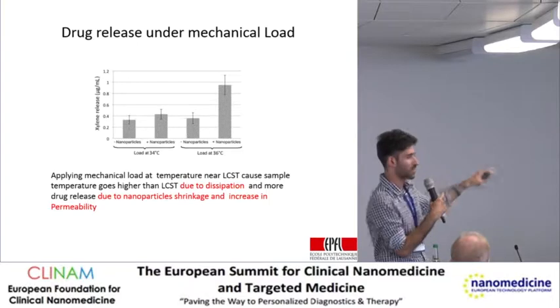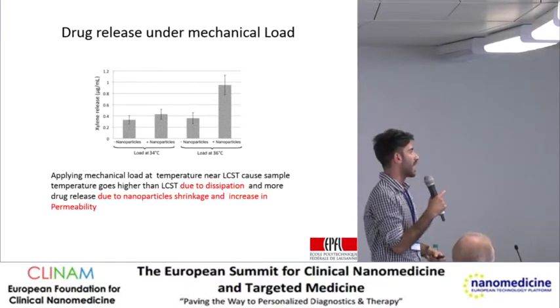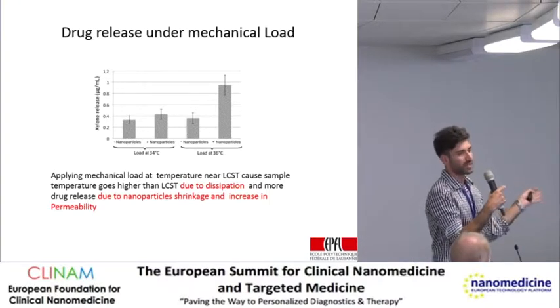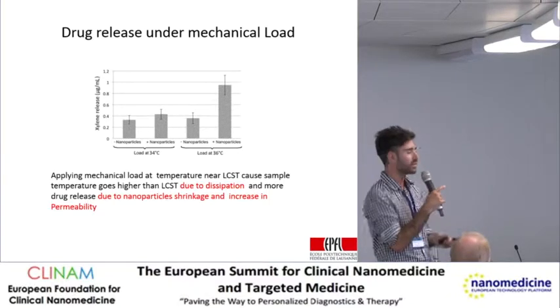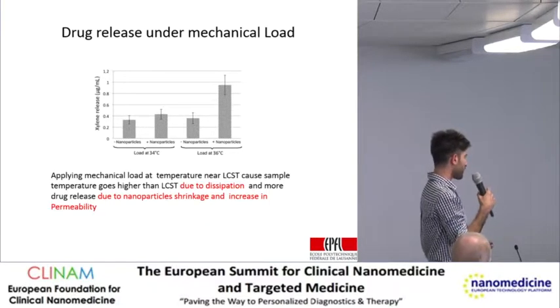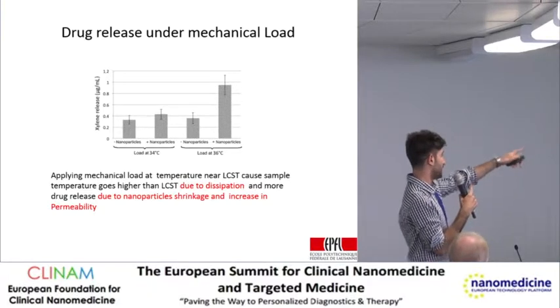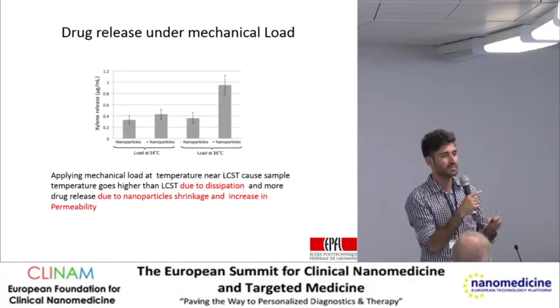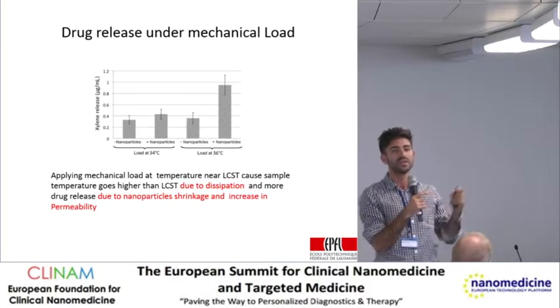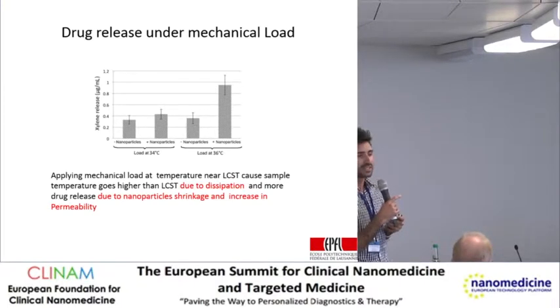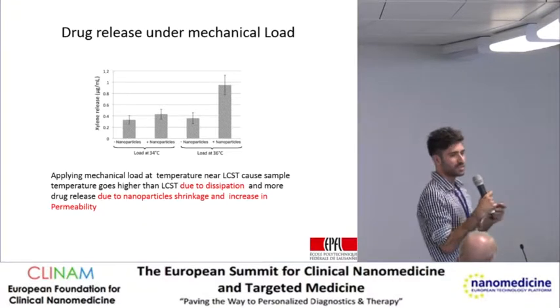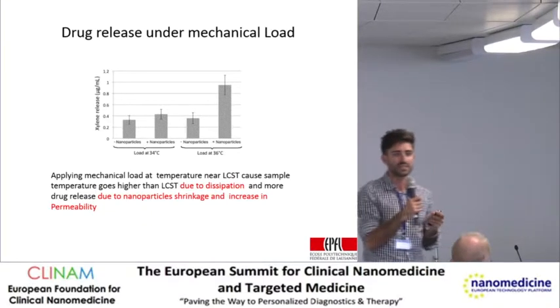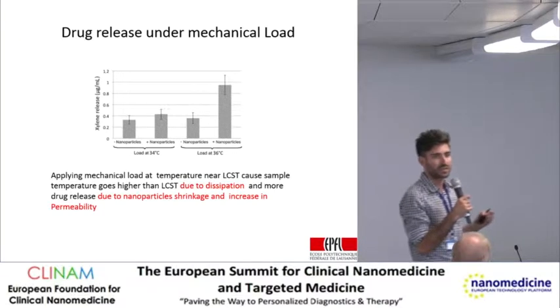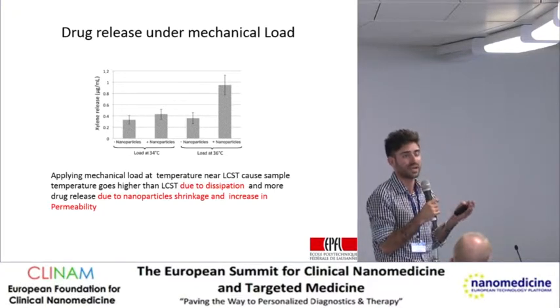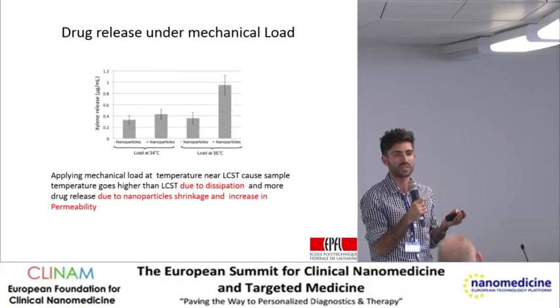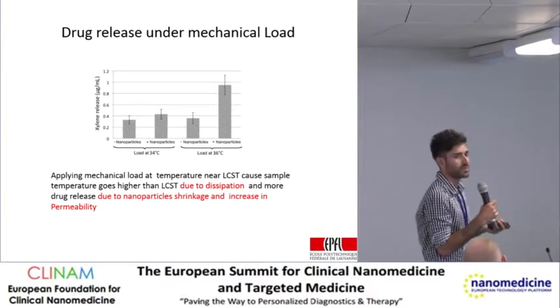So we control the release with mechanical load, and we provide a delay here of 5 minutes, but as I said, you can play with this delay to increase it. And the interesting thing is that the release that you have here compared to passive release is much higher, and this is due to the hydrophobic properties that our gel has, so that it doesn't have much passive release. So it's more the release under mechanical load, because the idea was to have mechanical load for release, favoring the release of the drug.